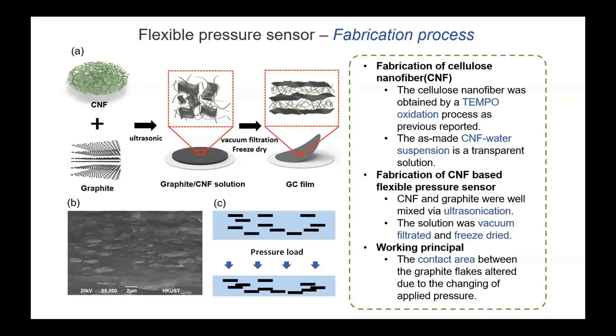The vacuum was then released and the damp film was first frozen at minus 40 Celsius degrees for 24 hours and then freeze-dried at minus 48 degrees for another 40 hours until the solvent was completely removed from the sample. Because of the directional ice templating, this composite is expected to have a well-aligned layered structure. The cross-section is shown here in the scanning electron microscopic image.